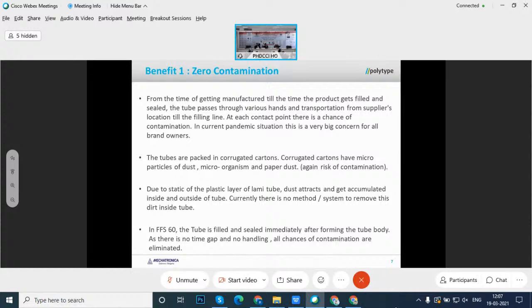Then, this tubular material, which is a plastic-based material, is very sensitive to static energy, because there is no conductive material inside. In ABL tubes you have this aluminum layer which somehow distributes these charges, but in plastic this is not possible. Therefore, in tube making, many times you do static discharging, but you can do this only from outside.